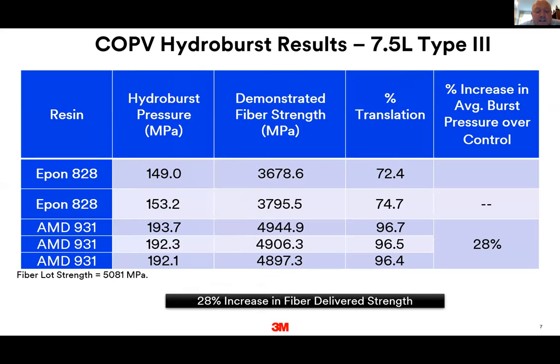It starts by looking at the performance of these resins in different tanks. We've done some studies where we put the resin into a traditional COPV and looked at what happens when you try to burst these vessels. As you can see, you get a nice improvement in the hydroburst result, which translates to an improvement in fiber-delivered strength. That is described by this percent translation increase when you compare it to the lot fiber strength listed on the C of A. So we see a nice improvement in fiber-delivered strength.